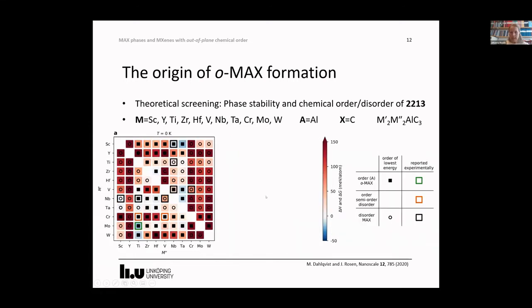So we do the same analysis for 413 alloys and possible OMAX, more precisely of a 2213 composition. The analysis, colors, and notation are the same as for the 312. In other words, we should look for squares with a bluish background if we look for new OMAX. Here is the only perfectly ordered OMAX that has been found to date, the Mo2Ti2. But at 0 Kelvin, there are several more candidates.